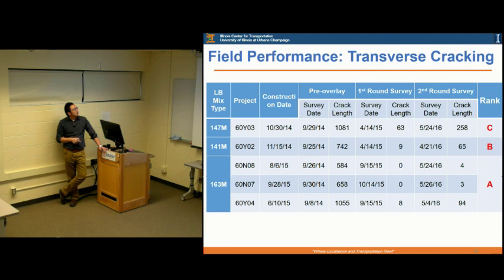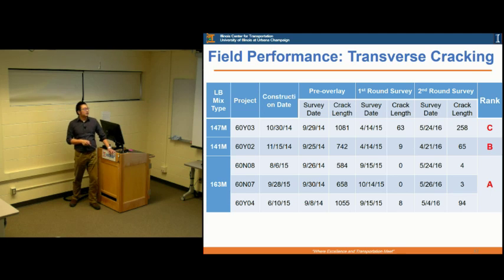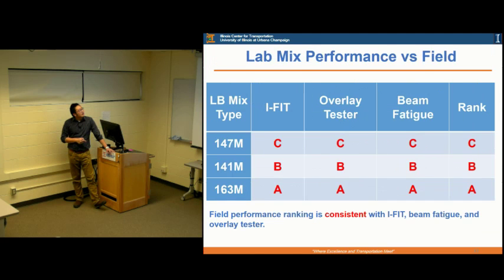We also got all the data here. Of course it's a big table, but what you can look at is that for the 3 contractors, the 163M mix has the best cracking resistance because it has the least crack length. So if we put the performance and field data together, you can see there's a very good consistency between the lab test results and the field ranking.